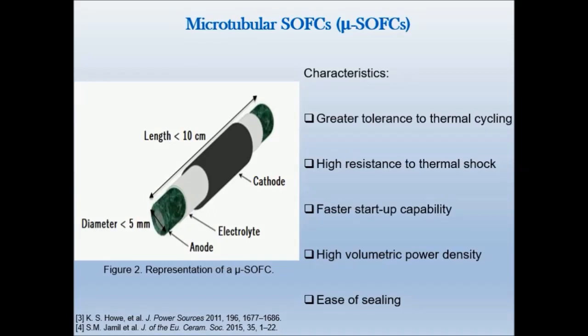Microtubular solid oxide fuel cells have been proposed for portable or mobile applications. Devices with this particular architecture have relatively small dimensions, length of tubes less than 10 centimeters, diameter less than 5 millimeters, and thickness of the cell components in the sub-micrometer range. Due to their small size, the temperature gradients in the stack could be relatively low, so that stacks of microtubular solid oxide fuel cells have greater tolerance to thermal cycling, high resistance to thermal shock, faster startup capability, besides higher volumetric power density and the ease of sealing compared to conventional tubular solid oxide fuel cells.